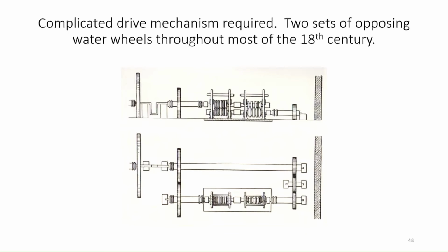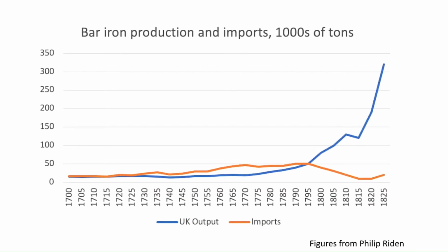Anyway, we come to the end because it's a nice point at which we can stop. You can see the result of this development. I mean, it's purely down to puddling and rolling that suddenly we were able to do with a lot less Swedish import. The Navy actually were very happy to use puddled iron instead of Swedish iron for its anchors and its chains. The imports continued because the Sheffield steelmakers weren't going to risk British puddled iron in their steelmaking. So they preferred to continue to buy in Swedish iron for its low phosphorus content. Now this finishes in 1825-ish.